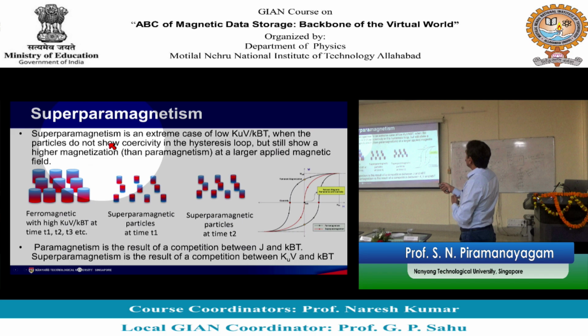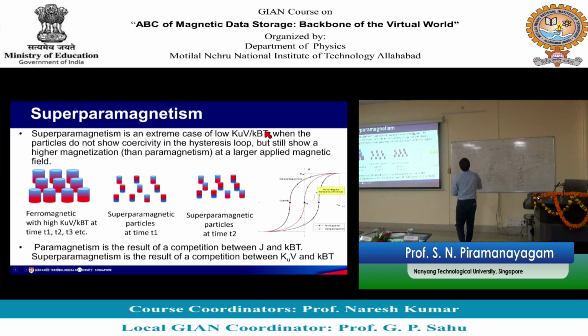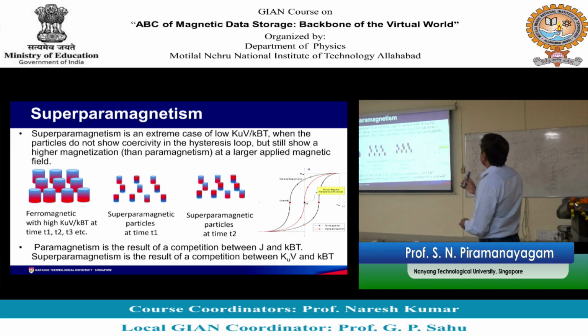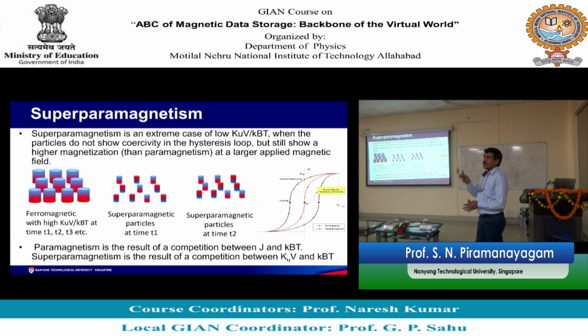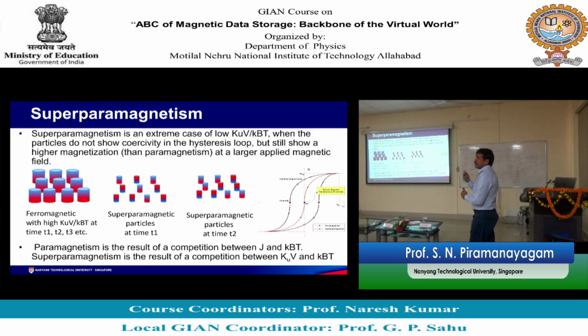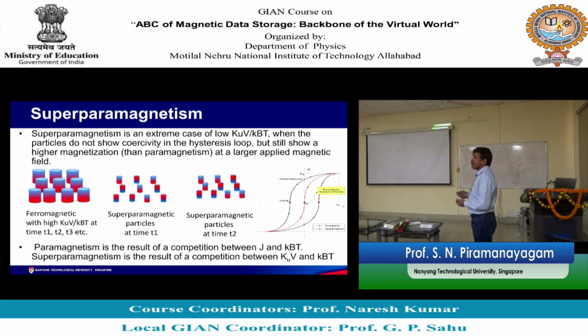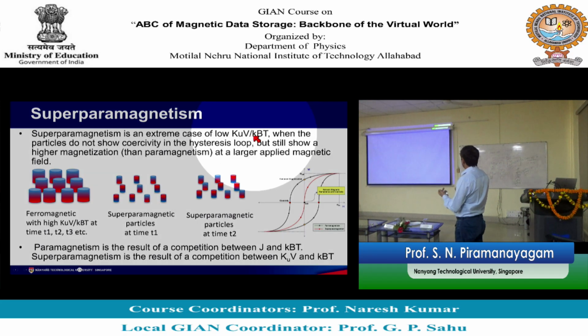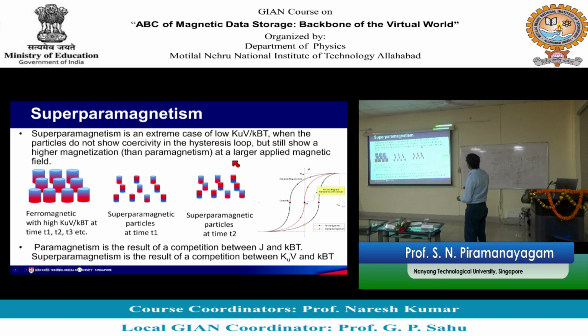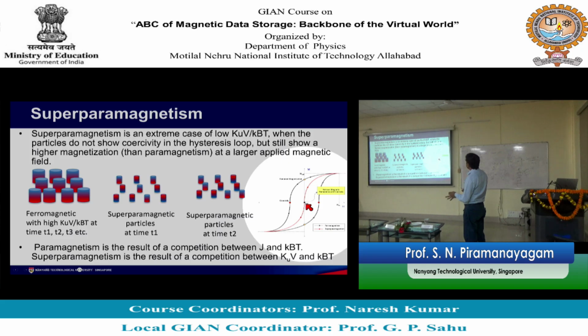So, you can say that superparamagnetism is an extreme case of low KUV by KBT. When I say how low, typically when you see that the KUV by KBT is below 20 or about 20, then all the magnetization will flip very rapidly. Very rapidly means in time scales smaller than seconds. So, it could be some milliseconds. Every millisecond they will flip as a function of time. As a result, if you measure the magnetic property of the sample, there will be no coercivity. So, they will just show a loop shown by the red color here. The magnetization will just increase or decrease, but there will be no coercivity.